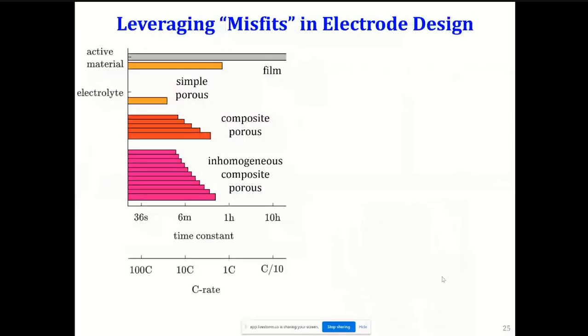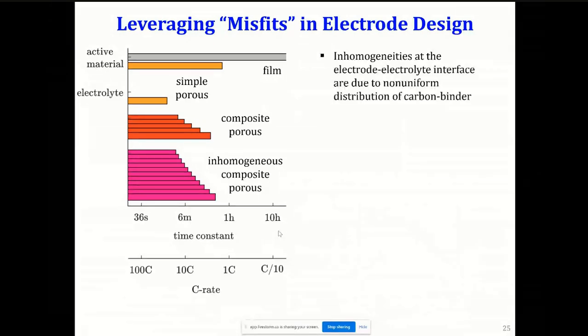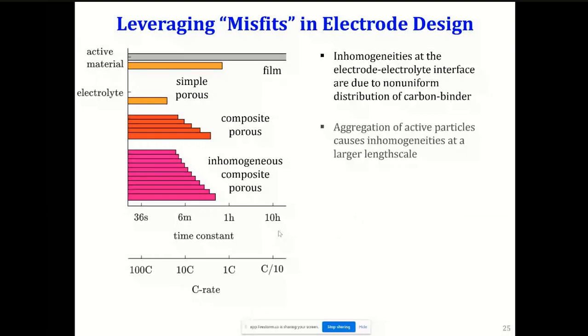So let me put this as a summary slide. And the key message I want you all to take away is that there are these time constants that we need to be aware of. And as we think of this next generation of design, we are going to be more and more limited by what happens at the interface, what happens in the pore phase, right? So we would run into two different types of inhomogeneities. One would be the inhomogeneities you would see at the electrode electrolyte interface, which is essentially because of the non-uniform distribution of carbon and binder. The second would be this aggregation of active particles, which gives rise to porosity gradients in the plane of the electrode, which would also give rise to a different kind of inhomogeneity, and in turn, a different kind of electrochemical, thermal, and chemical response.